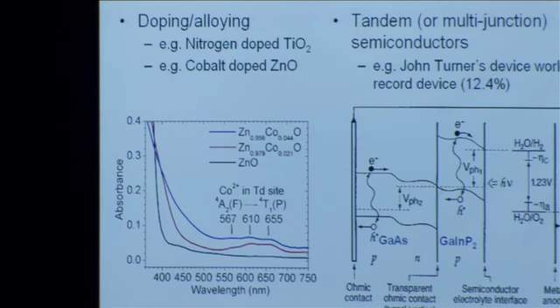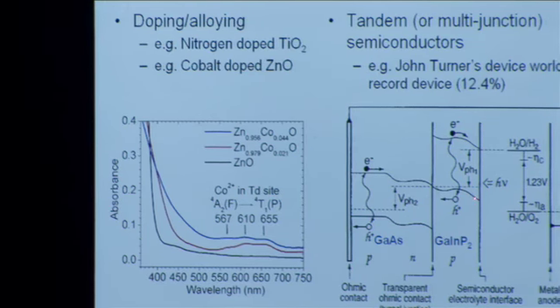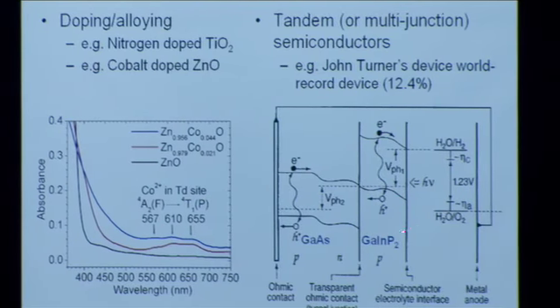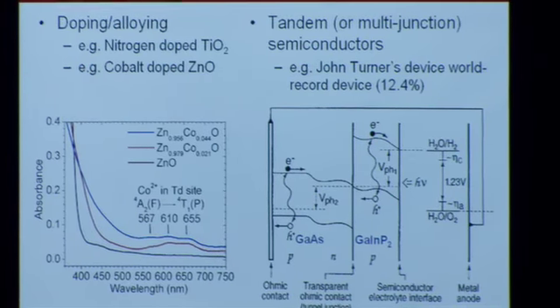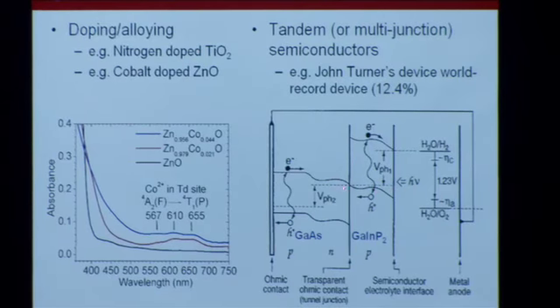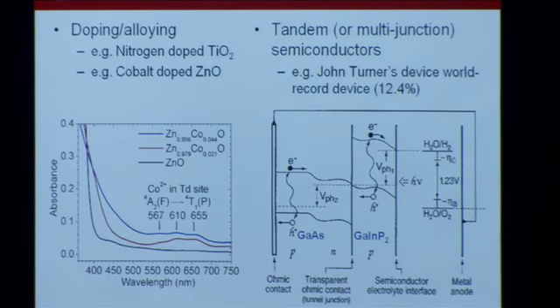Another approach that people have taken is using tandem cells, or in other words, multiple semiconductors, and this is exactly what John Turner did in that world record device. I mentioned he used a gallium indium phosphide p-type photocathode. You can see that the band positions for gallium indium phosphide are too high to split water. They're fine for the hydrogen evolution reaction, but these holes that are generated are not deep enough to pull electrons from water. So what did John Turner do? That's why he layered it on top of this gallium arsenide underneath it.